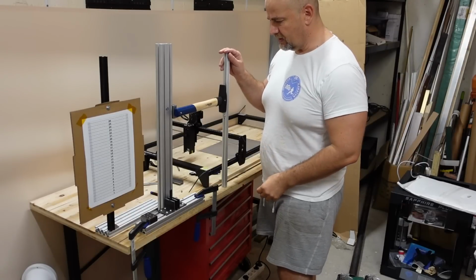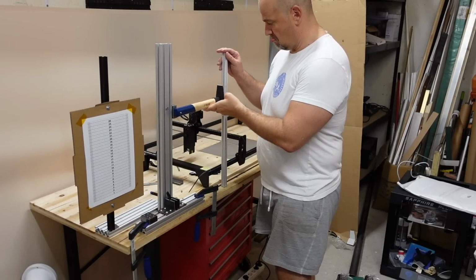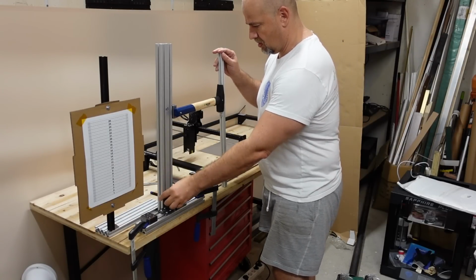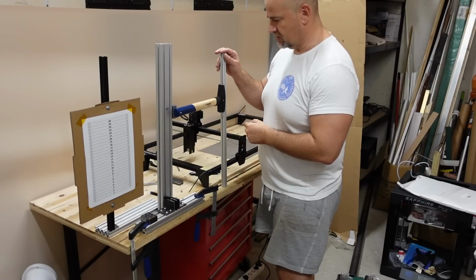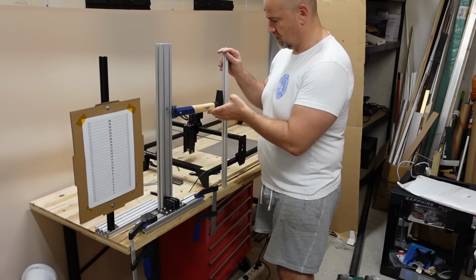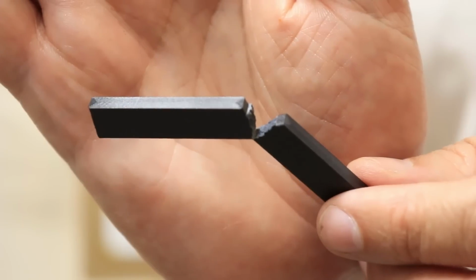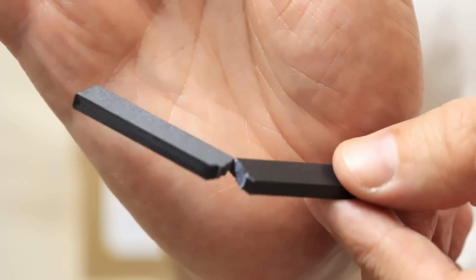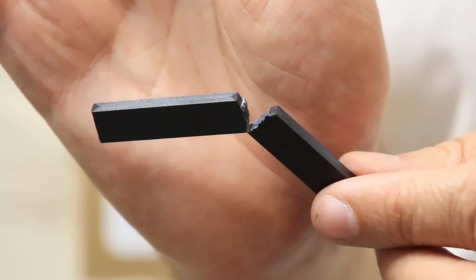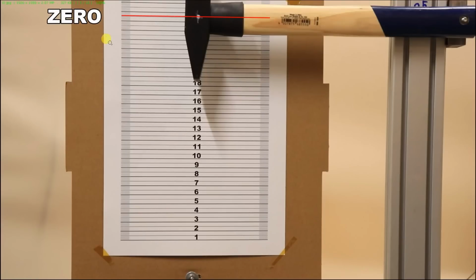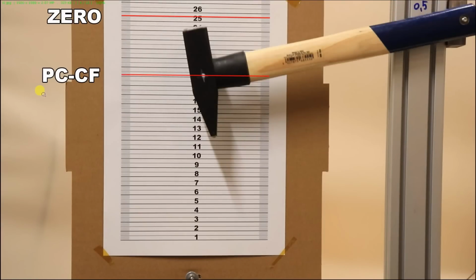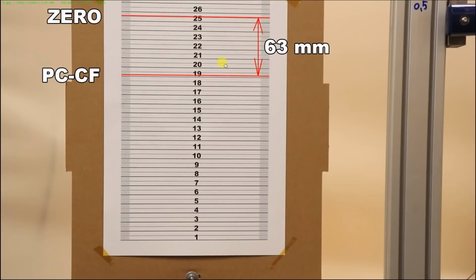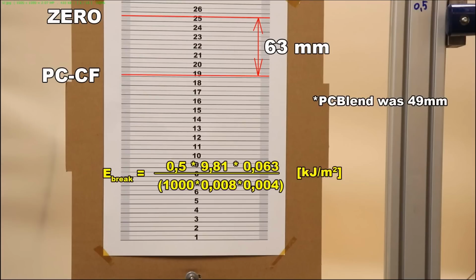Carbon fiber PC blend. Zero position. And it didn't break completely. But now let's see the numbers. This is the zero position, and this is after breaking the carbon fiber PC blend, and the difference in height is 63 millimeters. With the regular PC blend it was 49. And with this equation I can calculate the breaking energy.